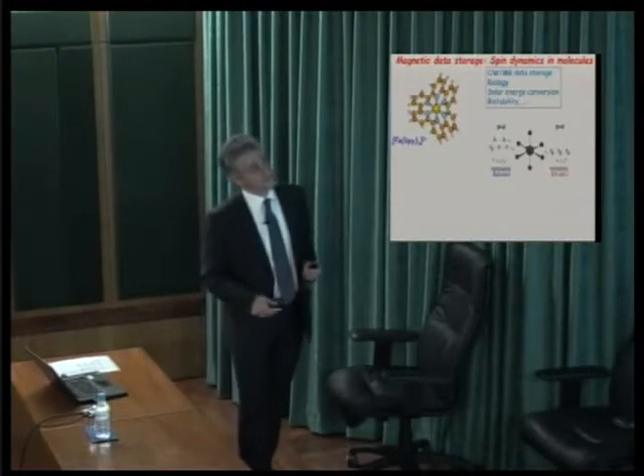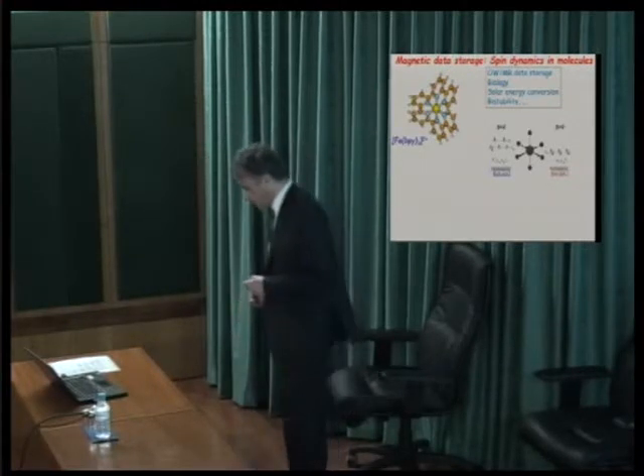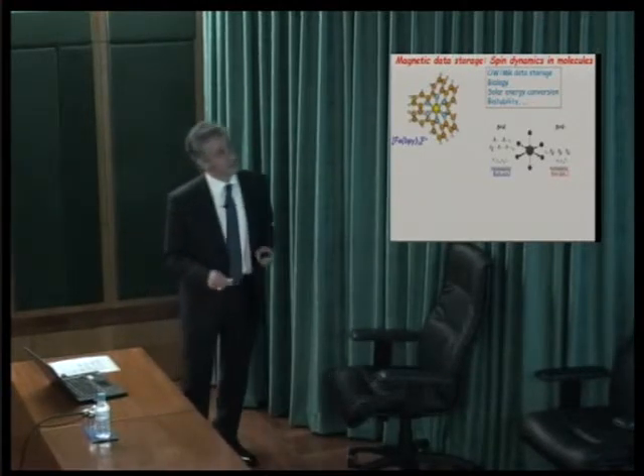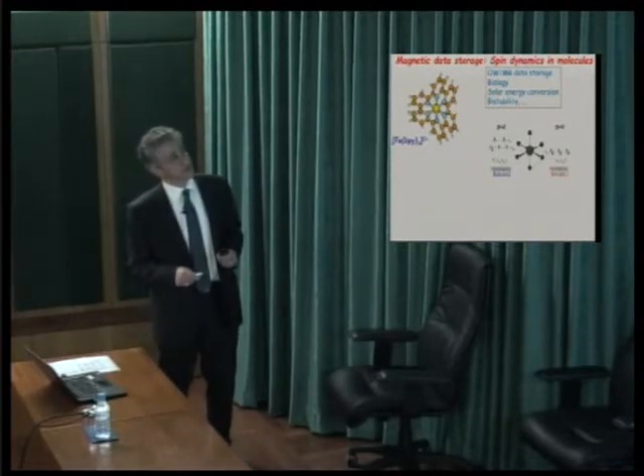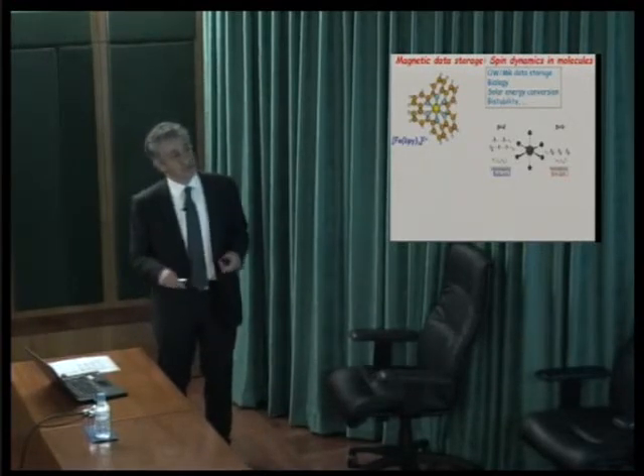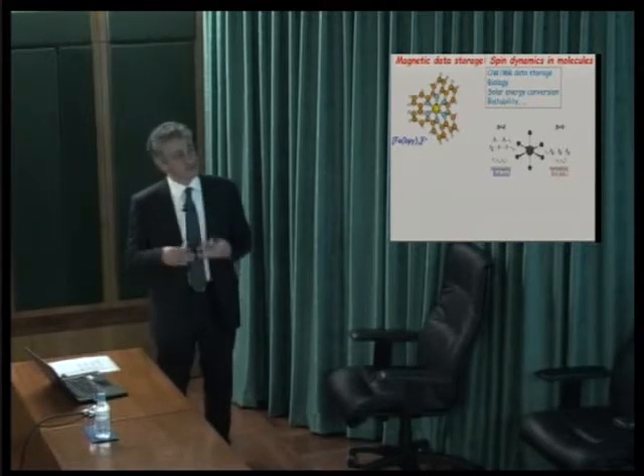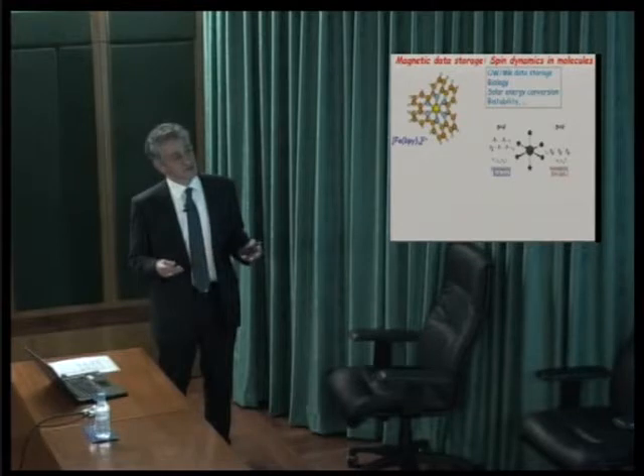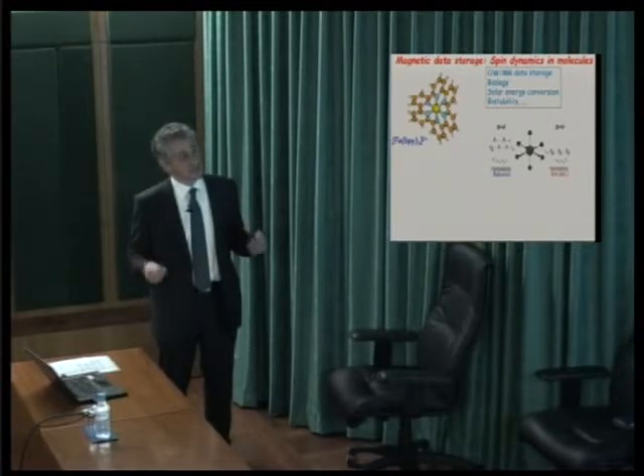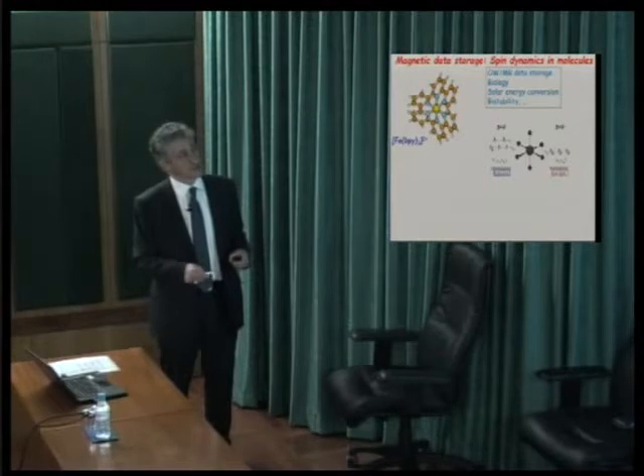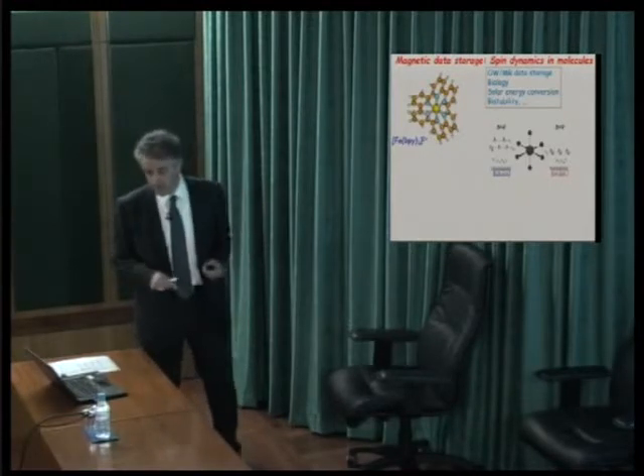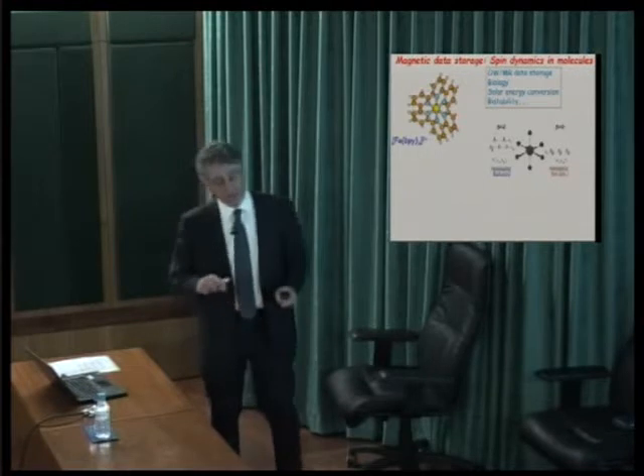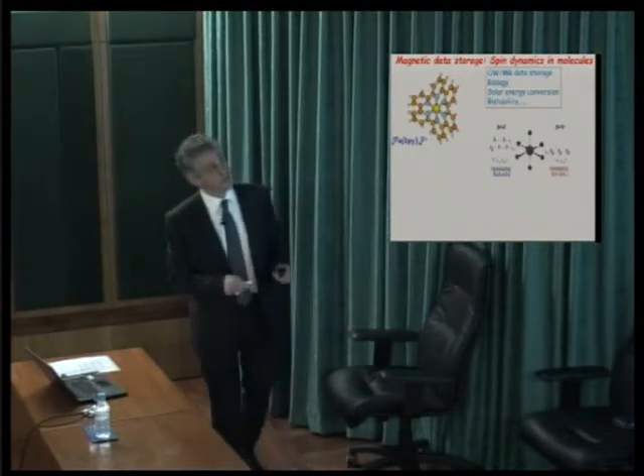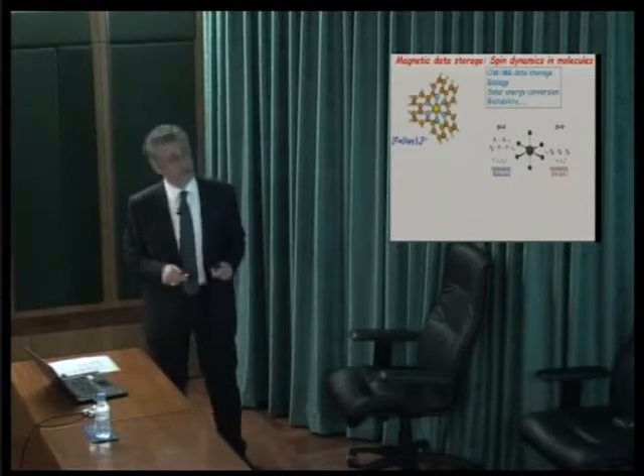So one of the first systems we focused on, and with which we demonstrated the femtosecond version of X-ray spectroscopy, was this family of molecules called iron polypyridine molecules. They are very important for spin dynamics because they can go from a low spin to a high spin state either by temperature, pressure, or light. This molecule in particular can only be triggered to the high spin by light. And these processes where you go from a low spin to a high spin state are very important for optical writing, magnetic reading of data storage.